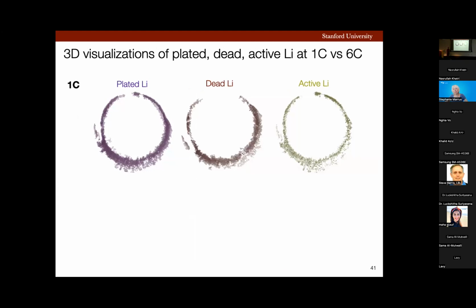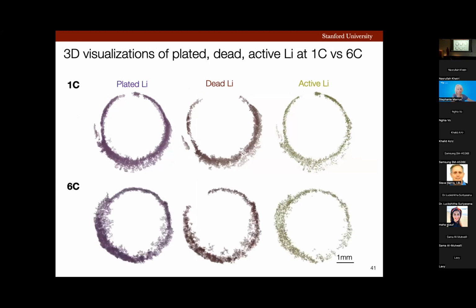By looking at these visualizations, you would notice that there are regions that didn't form any dead lithium. There are regions that formed a lot of dead lithium. There's also mossy nature of this morphology. By comparison, at 6C in plated lithium, we are seeing a more complete circle. We also see that this plated lithium has porosity associated with it. For example, there are nodules which are much denser as compared to the other nodules that are less dense. So this plated and dead lithium has varying density and porosity associated with it.